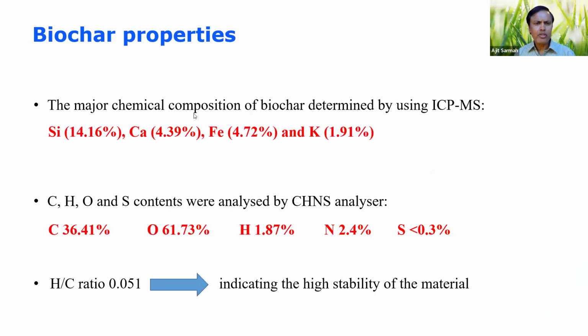So these are the biochar properties. The major chemical composition of biochar was determined by ICP-MS. Carbon, hydrogen, oxygen, and sulfur contents are given. And we use an aromaticity ratio of 0.051. The lower this value, the more stable the material is.